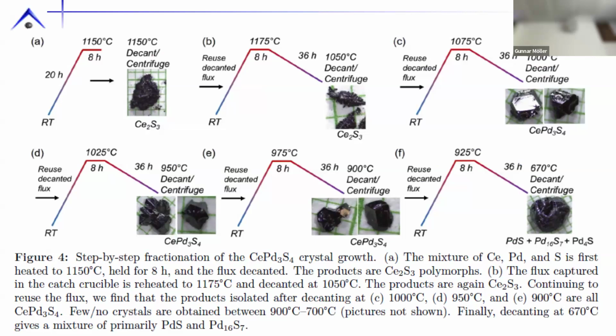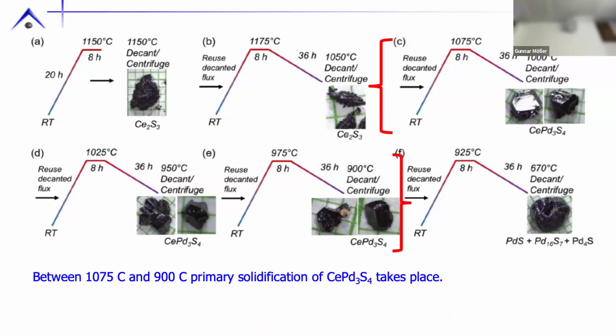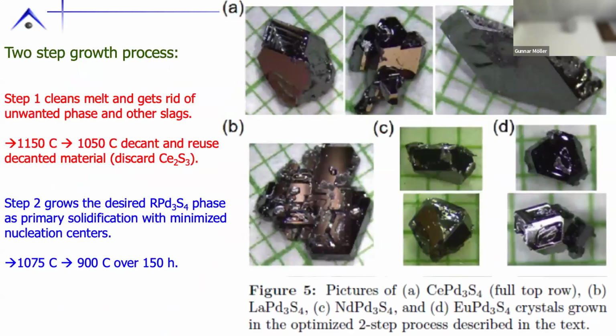Now to 1000, right phase. Reuse the decant. 1025, 950, right phase. Reuse the decant. 975 to 900, right phase. Reuse the decant. 925 to 670, wrong phases. So we were able to identify the key temperature region where we're interfacing with the liquidus surface for these materials. Okay, so what we could do then is come up with a two-step process. The first step, 1150 to 1050, gets rid of these unwanted binary phases, and more importantly, gets rid of any